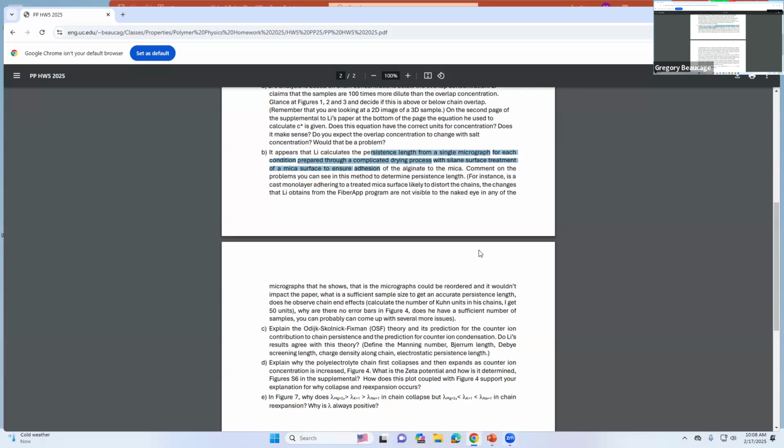All right, so there's a bunch of problems, right? I list some here. The way he makes it is a super dilute solution, like micromolar. And then he pours that over a mica crystal that he cleaves, and he treats the surface with a silane coupling agent that's got an amine functional group sticking up that's positively charged. I think he kind of pours his solution over that. So it's a tethering of the chains, which is known to change the conformation.